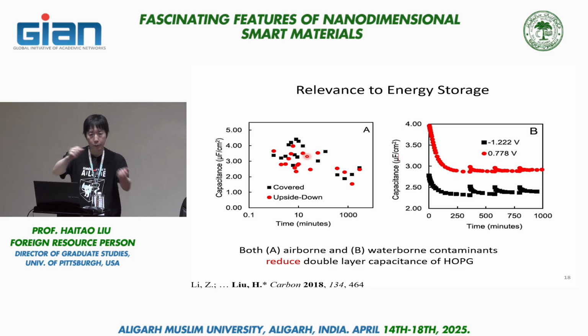And what we did is we exfoliate graphite, we leave it in air for a certain amount of time, and then we measure the double layer capacitance by EIS technique. Okay. And each data point on this corresponds to one separate exfoliation. So we did about 30 different exfoliations here.